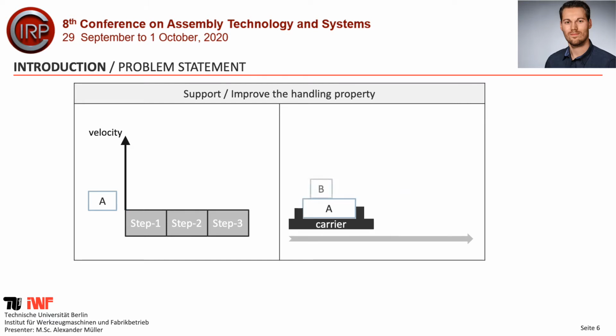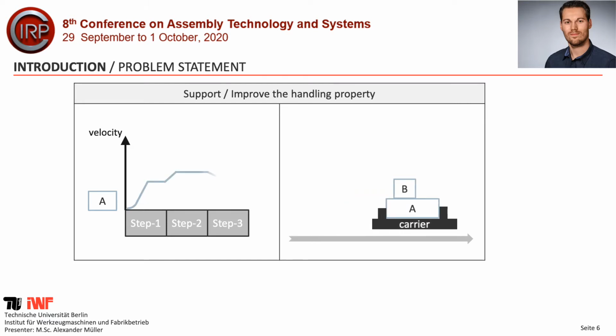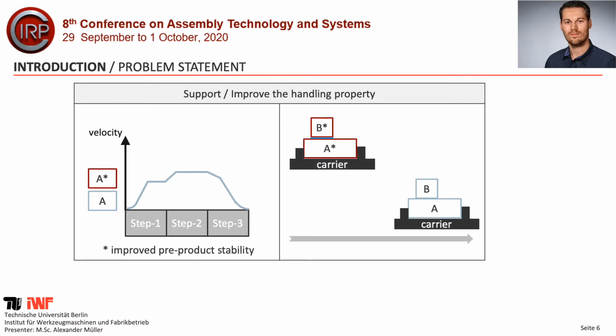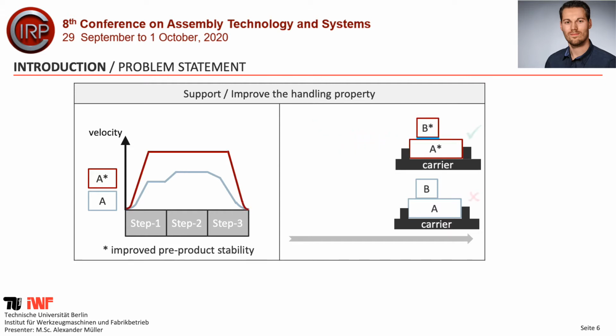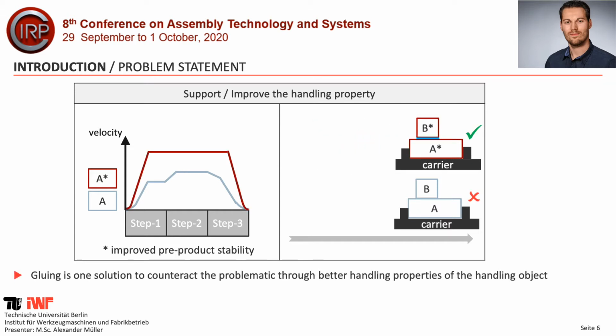But when you add another product on it, you have to look for a specific velocity curve, and you can avoid it when you improve the pre-product stability. In this case, you can glue these products together, and then you are able to drive with full speed again through the whole process. So gluing is one solution to counteract this problem.